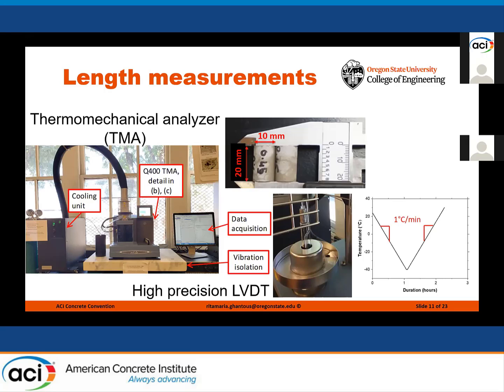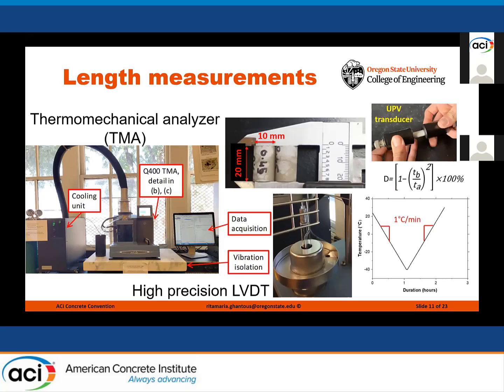In addition, to confirm the results we get from length change measurement, we did ultrasonic pulse velocity measurement on the same sample before and after freezing. We measured the ultrasonic pulse velocity right before we put the sample in the thermomechanical analyzer and after we took it out, so after the freeze-thaw cycle. Then, based on the equation here and the reduction of the ultrasonic pulse velocity, we calculated the damage index according to the equation shown here. That is also an indicator of the freeze-thaw damage.